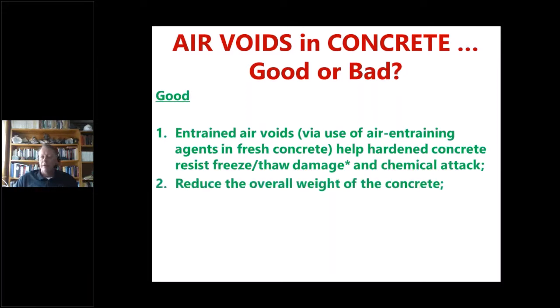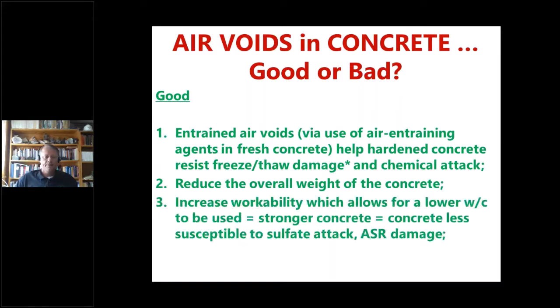Number 2, the more air you have in the concrete, you're obviously reducing the overall weight of the concrete. There's a point where that's counterproductive, but generally speaking, the more air you have, the less your concrete will weigh. Number 3, the more air you have in your concrete, you can still be able to work the concrete, but with a lower WC, lower water to cement ratio.